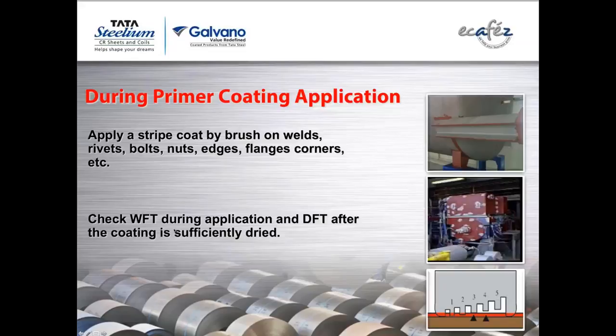Now again, going back to the earlier slide, I mentioned that you should have the product data sheet from the paint manufacturer. This product data sheet will also tell you the volume solids. That means after evaporation of thinner from that paint, how much volume is going to remain as dry paint film. Taking that into consideration, you have to use this WFT gauge, wet film thickness gauge. It is a comb type. There are two other types also available. Now I have to spray and immediately dip it and check. On that you will find 1, 2, 3, 4, 5 in this picture. Those are mils. One mil is 25 microns. So 25, 50, 75, 100, 125 are there on this gauge. You get it up to 2000 microns also.